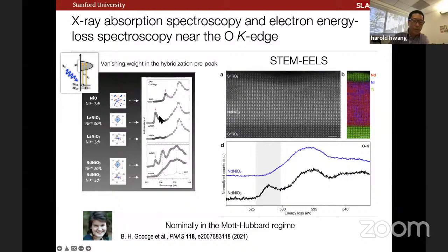So just to highlight one of the features that's relevant, if we take nickel oxide or the perovskite nickelate, and you look at the oxygen K edge, you see this strong, well-known pre-peak feature that's associated with these contributions. But if we go to the infinite layer phase of lanthanum or neodymium, this is largely absent. So this is XAS, and similarly in EELS, you can see this dichotomy between the perovskite and the infinite layer phase. The other broad statement, these are very approximate statements, of course, and there's some debate still going on in the field, but this is closer to an intermediate or approaching the Mott-Hubbard regime in terms of this band alignment, as I just sketched for you in the previous slide.